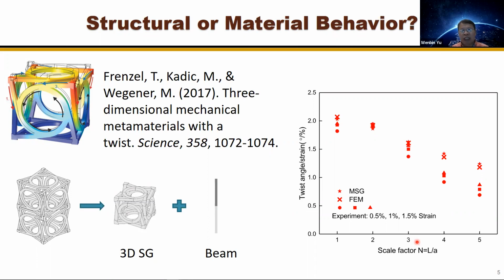But the twist behavior only exists when you have only a few unit cells along a certain direction. For example, you stack them together along one direction, it's kind of like a beam, a metamaterial beam, or stack them together along 2 dimensions, it is a panel, then you have the extension-twist coupling behavior. But if we stack them in all 3 dimensions, repeat many times, then the twist behavior will disappear. So it's really not a 3-dimensional material property. What I will call it is a structure behavior. To generate the extension-twist coupling at the structure level is pretty easy. And we can use regular laminates to generate that kind of behavior.